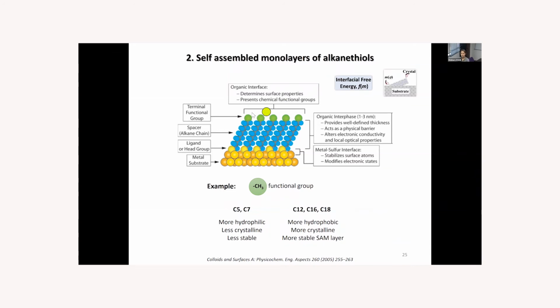The organic interface functional groups determine the surface properties, which can be hydrophobic, hydrophilic, oriented in one way or another. The SAMs can be less or more crystalline. As was shown for the CH3 functional group, where the author studied the influence of the alkyl chain length on the hydrophilicity, crystallinity, and stability of the SAMs, you could see that for the short chains, the SAMs were more hydrophilic, less crystalline, and less stable. And for the longer chains, the SAMs were showing more hydrophobic behavior, were more crystalline and more stable. So there is a give and take for our SAMs here.